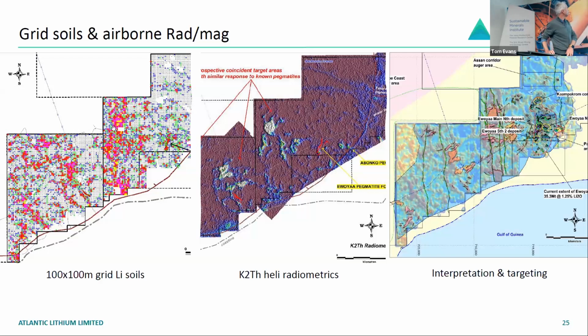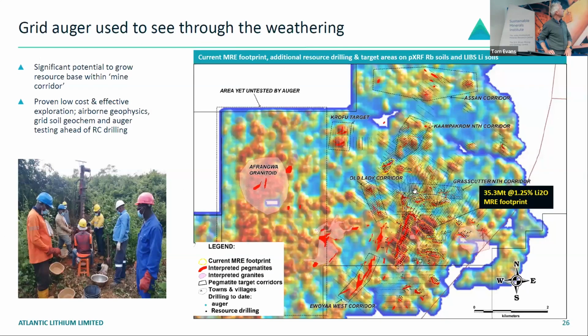So here we can see again the soils and the levels I spoke to before. The yellows are at that 1,500 up to 9,000 ppm. And then Ewoyaa itself, which sits here, is that 300-400 ppm to about 600-700 ppm in soils for lithium. So using those geophysics and then mapping on the ground to highlight our target areas, and then coming in with auger, this has been a really invaluable tool for us. We've got anywhere between 2 up to 6 augers working day in, day out. It's also a good employment tool for the youth within the communities. So that really works in our favor and their favor as well.